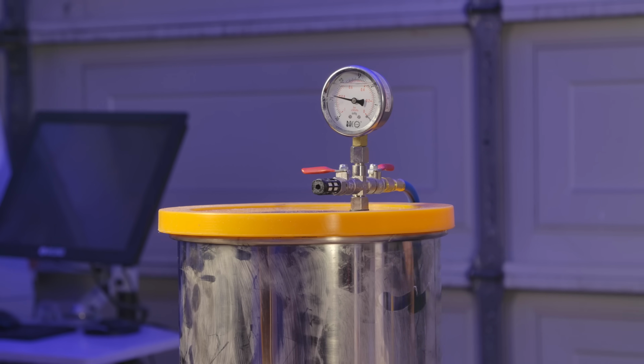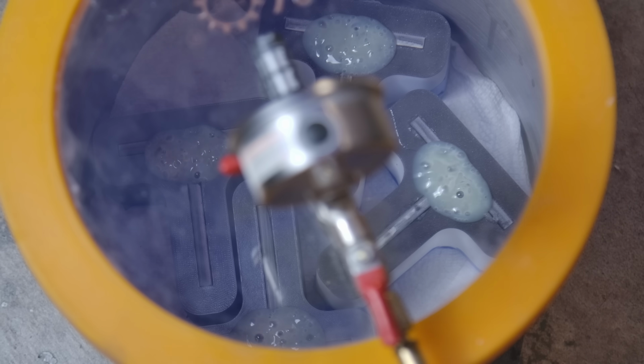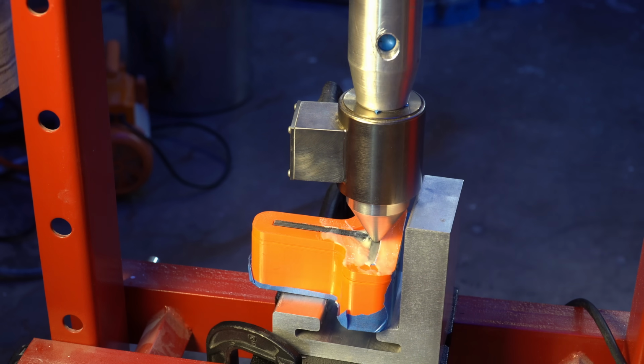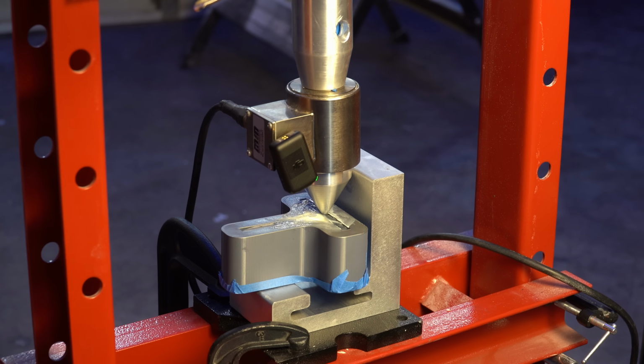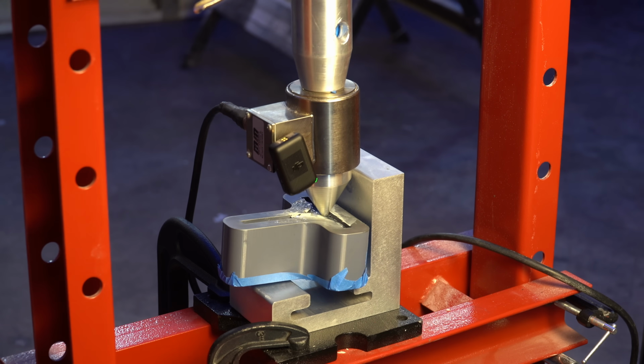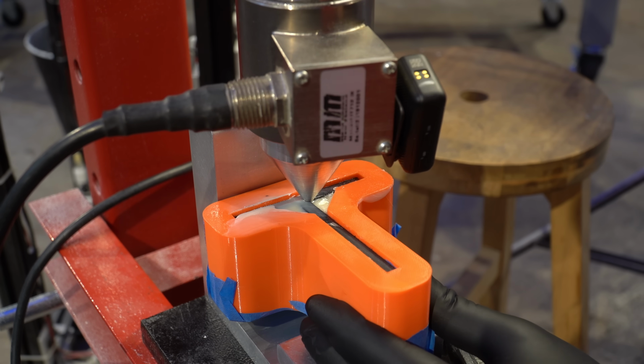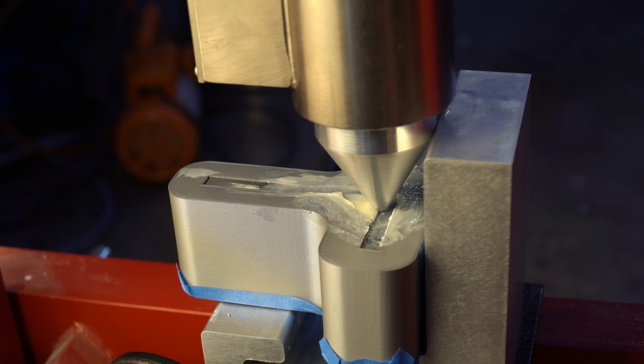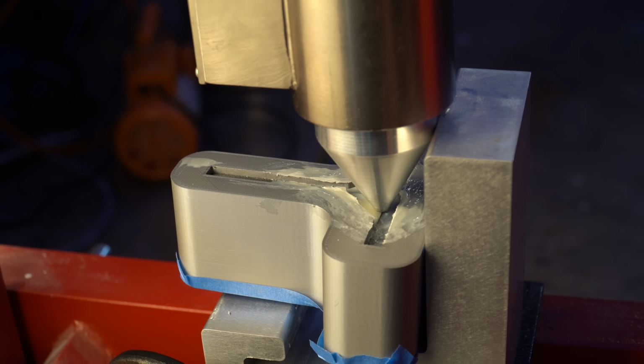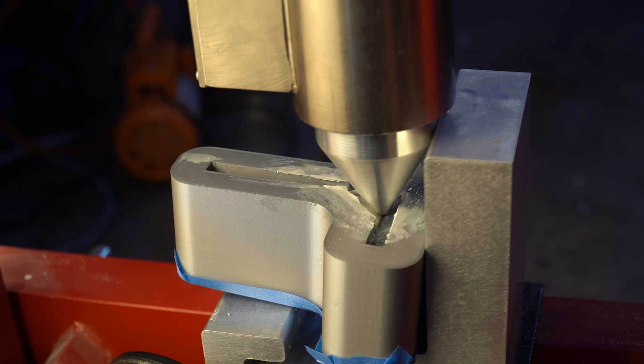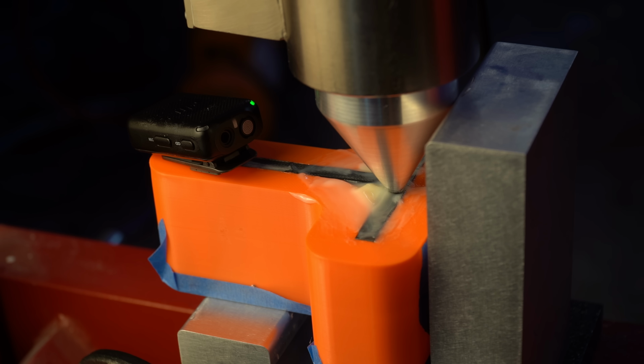It usually took a few iterations of this to get the epoxy to not bubble over the top of the mold and spill everywhere. Once cured, the superlube as a mold release kind of worked. It required some extra force to extract it every time, but nothing close to the breaking strength of the epoxy, so I wasn't too concerned. The cracks you hear in these clips are tiny pieces of epoxy fracturing, but most of the bond should be fine.